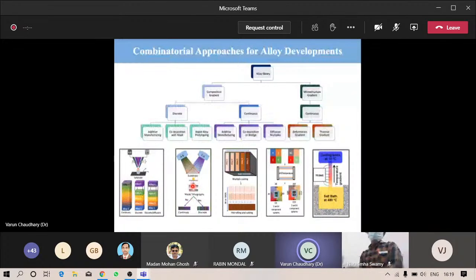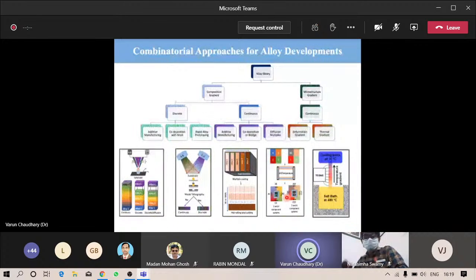In the case of co-sputtering, this is only suitable for thin film kind of samples. The third one is rapid alloy prototyping. This is limited in that we can only have a few compositions at one time. Another is the diffusion multiples. This is again very time consuming. It takes sometimes weeks and months to get a proper diffusion. So here we are working on the first two techniques, and today I'll present the results only on additive manufacturing.